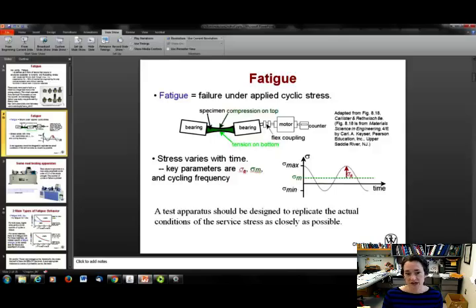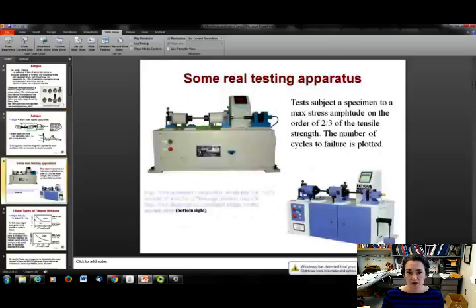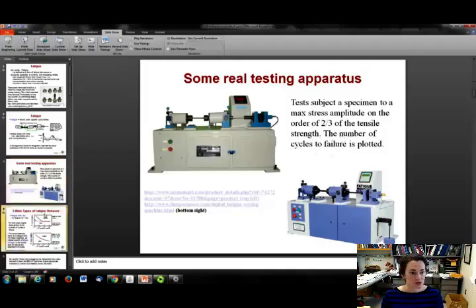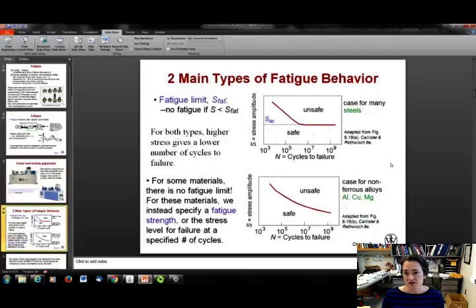Of course, you want to replicate the actual conditions of service as closely as possible. Here's some images of some testing apparatus that I found online. Basically, the tests will subject a specimen to a stress amplitude that's on the order of 2/3 of the tensile strength, and then what you do is plot the number of cycles to failure versus the stress. So here's a couple images of those plots.